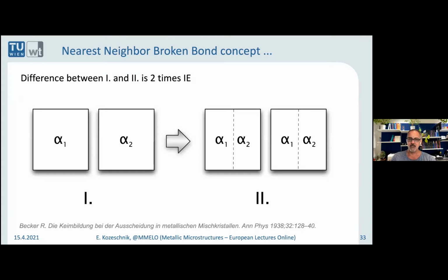You simply go back to the really old great guys. The one who discussed this interface energy calculation first was Richard Becker, 1938, so that's quite a long time ago. In his paper, he proposed the idea that the interface energy can be calculated from a thought experiment, which is on the screen. Take two phases, alpha 1, alpha 2, cut them in the middle and assemble them with the other part. Then the energy difference between the left and the right state is simply 2 times the interface energy of the system. And the task is now, how can we calculate that?